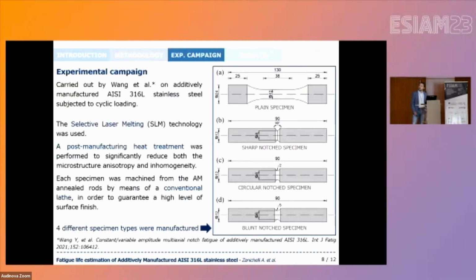So let me now briefly describe the experimental campaign used for the verification of the proposed methodology. In particular, we consider the experimental campaign carried out by Wang et al. on additively manufactured AISI 316L stainless steel, subjected to cyclic loading. During this experimental campaign, the selective laser melting technology was used, and a post-manufacturing heat treatment was performed. So then each specimen was machined from the annealed rods by means of a conventional lathe in order to guarantee the same surface finish to all the specimens.